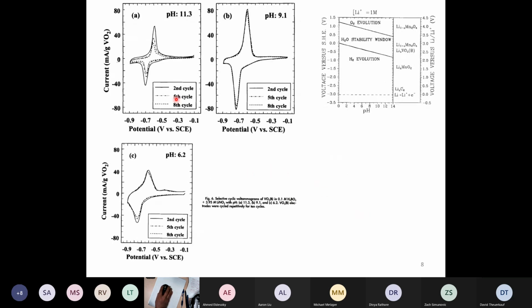Anyway, one of the things that we did learn was when we did cyclic voltammetry with this vanadium oxide electrode, if we operated at high pH, every time you did a cyclic voltammogram sweep, the signal would get smaller. And this meant that the material was dissolving in the electrolyte. And sure enough, if you analyzed the electrolyte afterwards, you found vanadium in solution. And as you lowered the pH, you would get more stability, but still, you could see the voltammogram still shrinking in terms of its height. And that means there's active material loss happening. And at pH 6.2, still shrinking over the first 8 cycles.